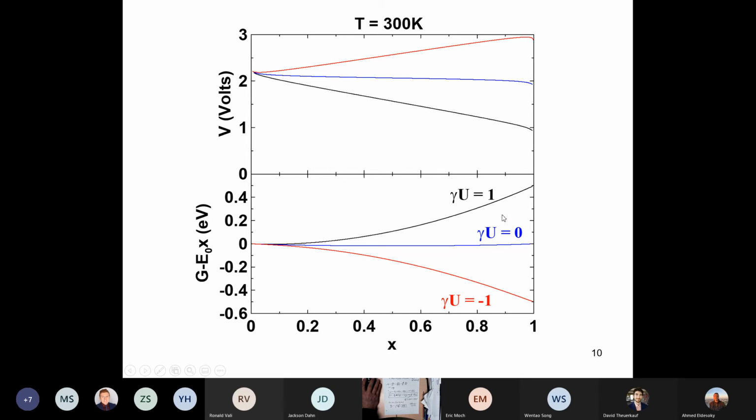All we have here is first neighbor interactions, and the blue curve is for no interactions, so the only thing happening is the entropy effect. It's almost like what we calculated for the t equals 0 case, which was a straight line, except because of this entropy, there's a small slope, and at the ends there's quite a steep slope, as you can see there.